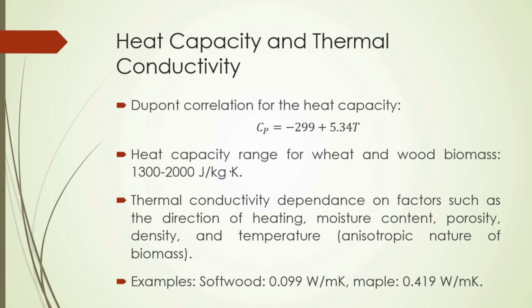DuPont provided a correlation for the heat capacity of dried agricultural residues with particle sizes below 200 micrometers over a temperature range of 40 to 80 degrees Celsius. Heat capacity equals -299 plus 5.34 times temperature, where heat capacity is in joules per kilogram Kelvin and temperature is in Kelvin.